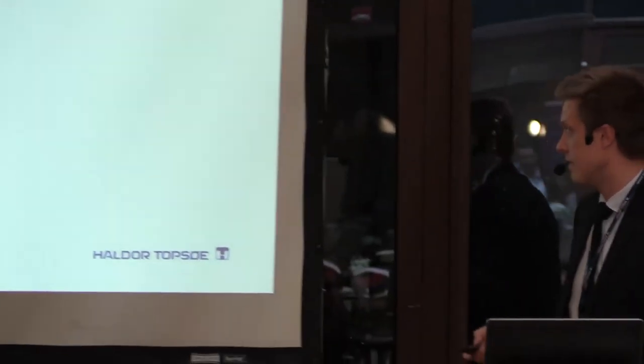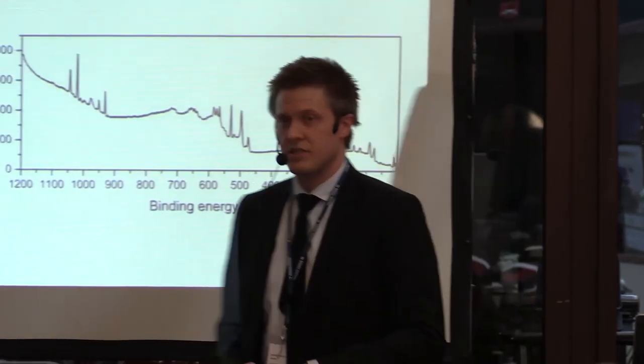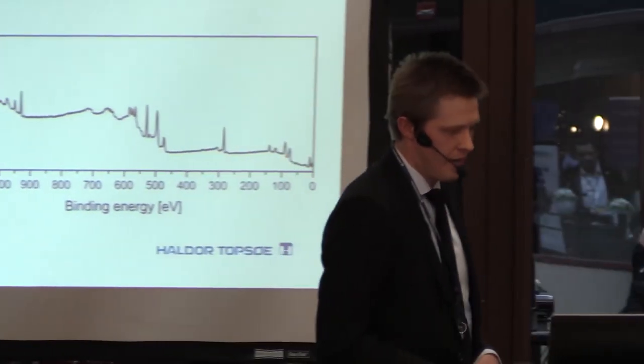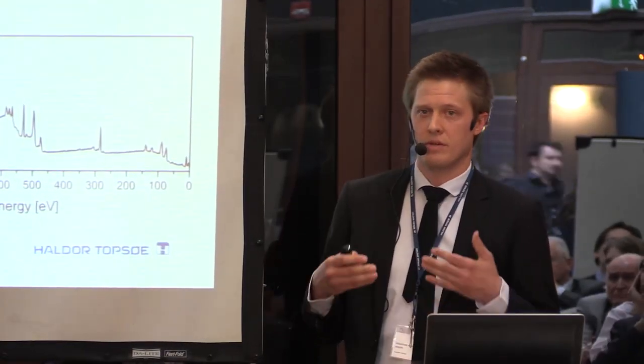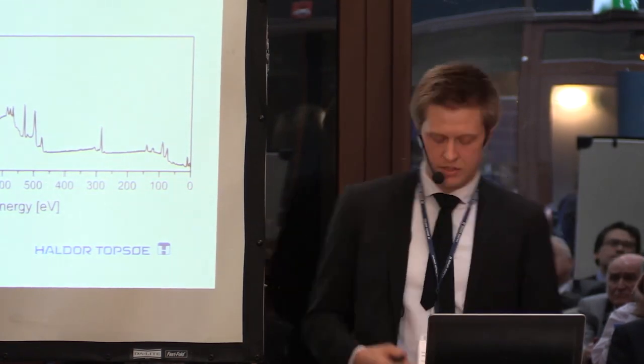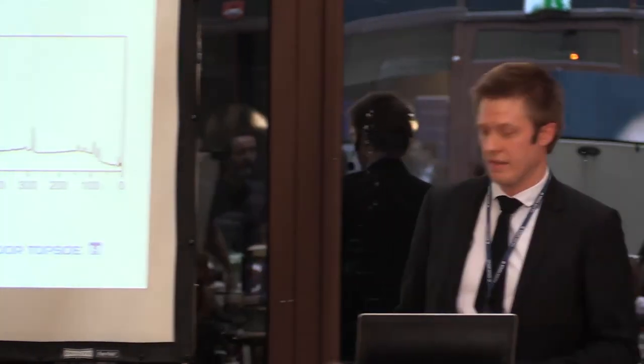Here we could illuminate the surface with X-rays. These X-rays will interact with the catalyst and emit electrons, but only electrons from the outermost surface of the catalyst will be collected by the analyzer. So based on the energy of these electrons, we can get a spectrum like this. And this spectrum contains some chemical information about the elements in the catalyst and also about the chemical environment that these different elements are sitting in. So by analyzing these spectra, we can actually distinguish if zinc is sitting next to an oxygen atom or if it's sitting next to another zinc atom. We can see if it's an oxide or if it's a metal-metal bond.